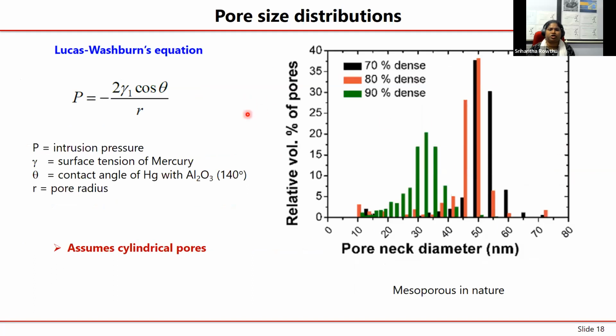Then we also wanted to characterize the pore sizes, right? For that we have used the mercury intrusion porosimetry method, and this is the so-called Lucas-Washburn equation, which says that mercury is a metal, and it has a surface tension of around 480 millinewton per meter. Why am I talking about surface tension? If you have a very, very high surface tension of a liquid, then it prefers to be in a spherical shape. It doesn't like to wet the solid.